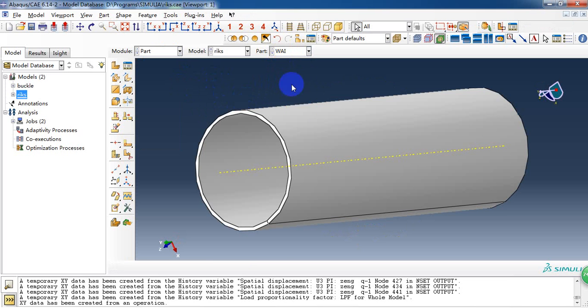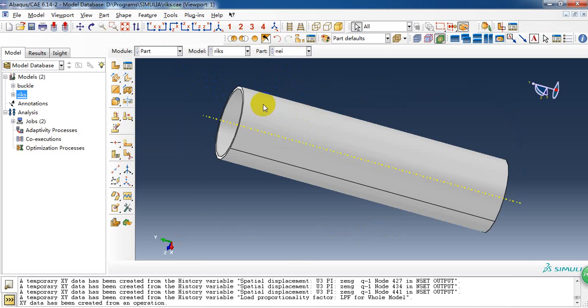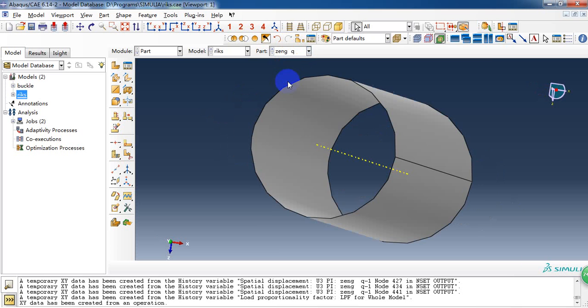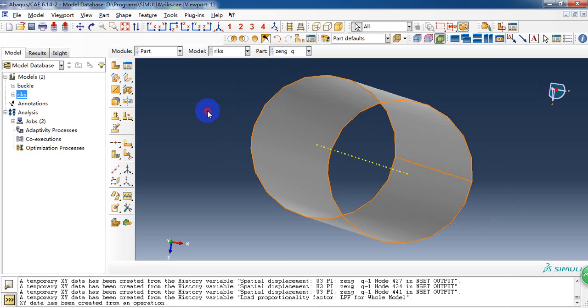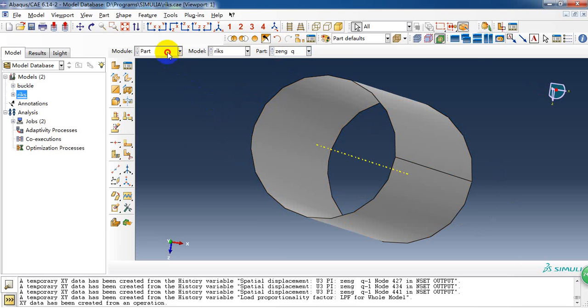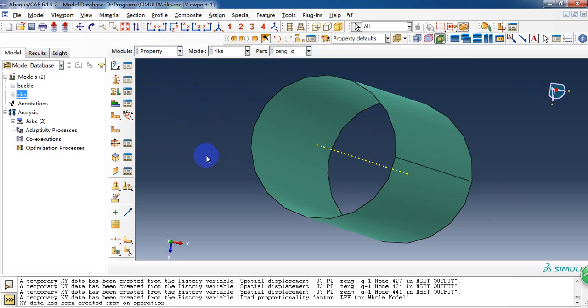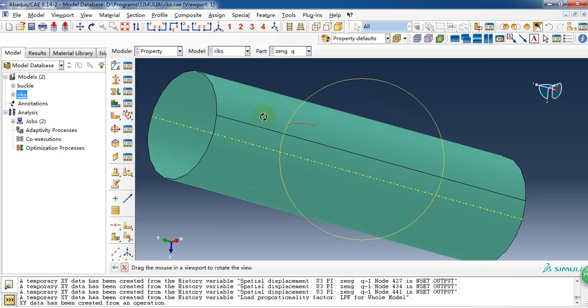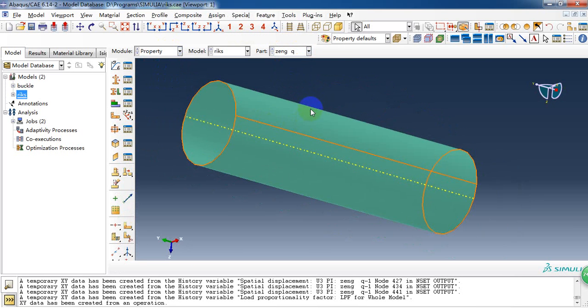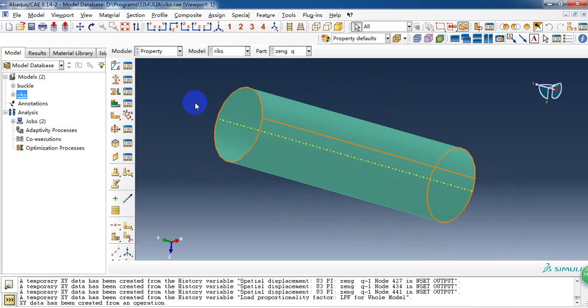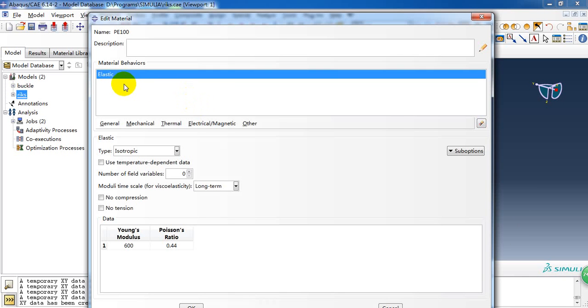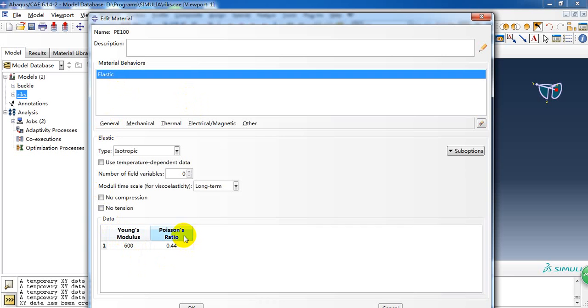The outside tube, inside tube, and the middle composite layer. So there are two kinds of materials we need to define. Here is the PE material. We make it as elastic material. Here's modulus is 600 megapascals. And the Poisson's ratio is about 0.44.